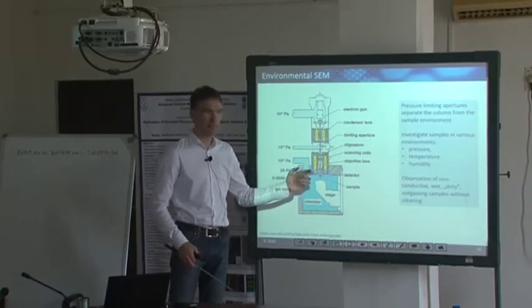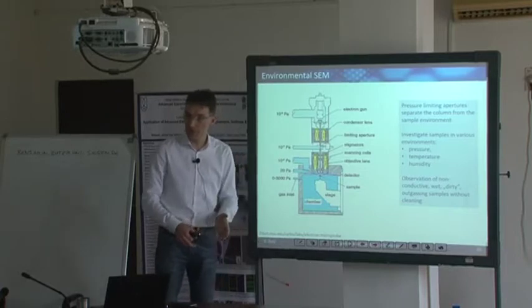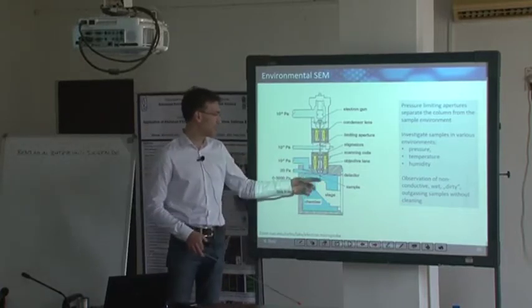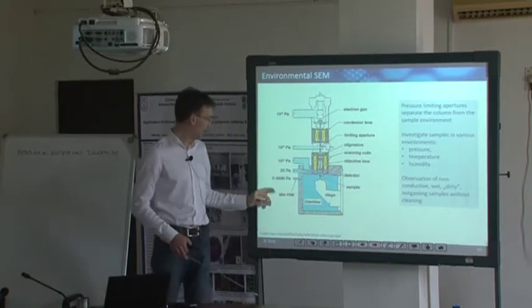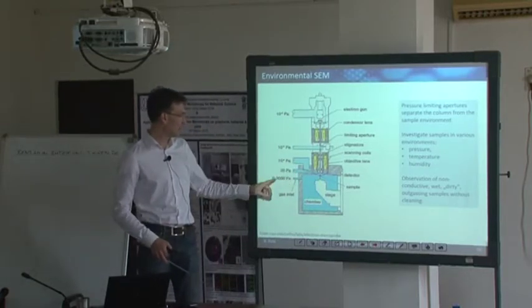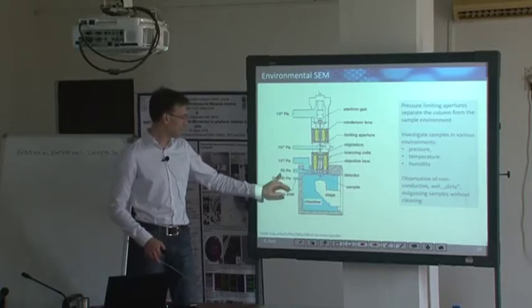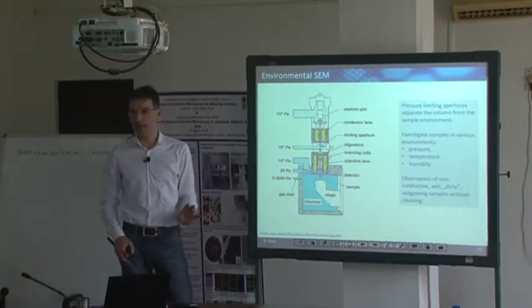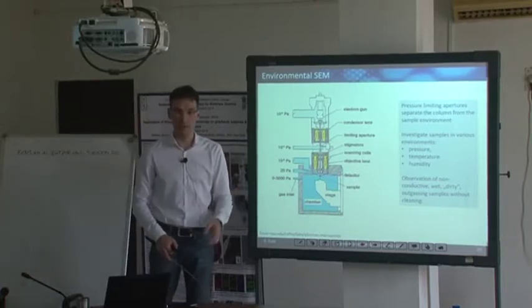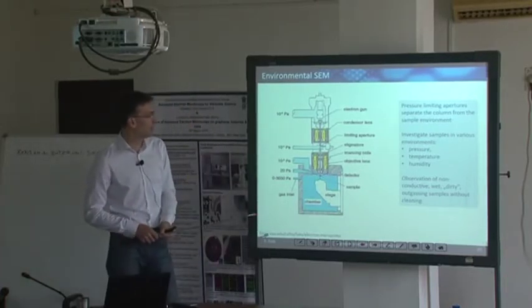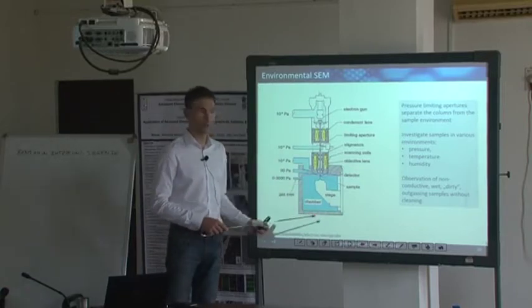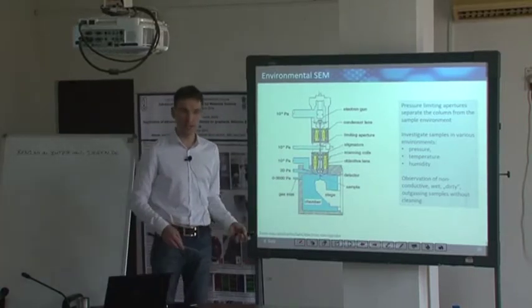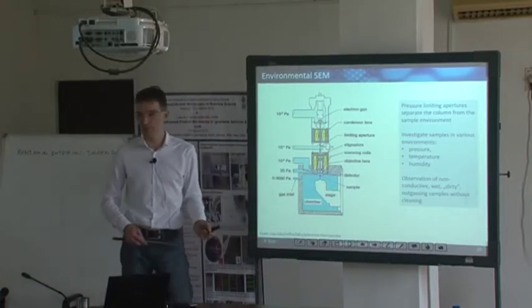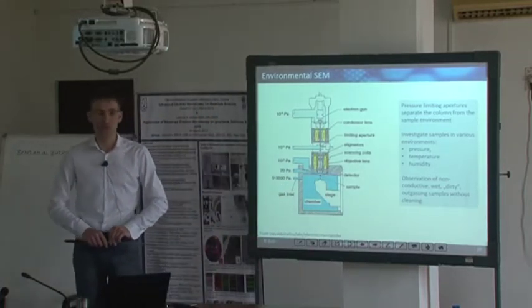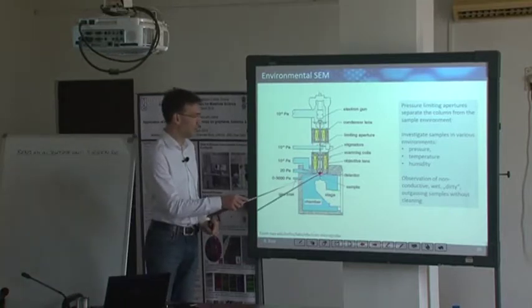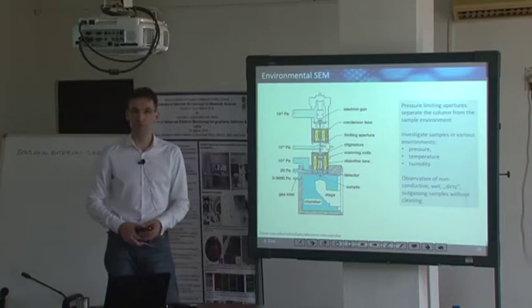Any inelastic and elastic scattering would cause a broadening of your beam in a scanning electron microscope, but only up to a certain pressure. In this particular case, it goes up to 3,000 Pascal. This is 30 millibar. 30 millibar is not a really high pressure compared to 1 bar, to 1 atmosphere. But people introduce humidity, water vapor, or just gases like hydrogen, oxygen, nitrogen. It depends on what you're interested in. What you have here in between is a so-called differential pumping aperture.